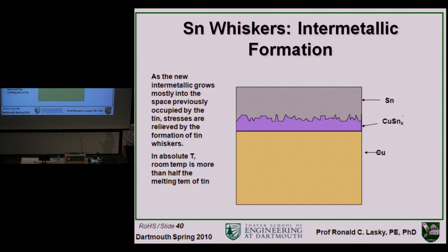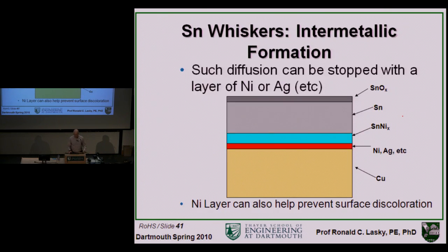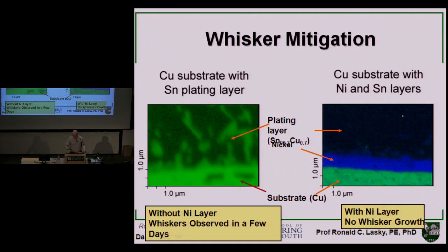The copper goes in this direction and creates compressive stress here because we have material flowing in. And actually you can get a reduction of copper at this interface, which probably some of you have heard of. They're called Kirkendall voids. And so one of the ways people minimize this is you can put a nickel or silver interface between the tin and the copper, and you'll form a tin nickel intermetallics, and there's nowhere near as much copper diffusion and additional compressive stress creation in the tin.